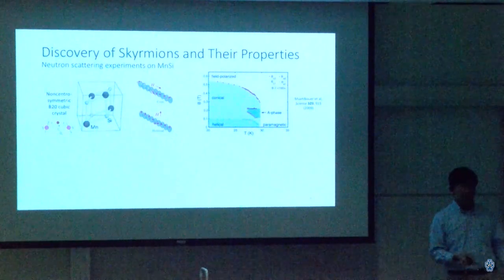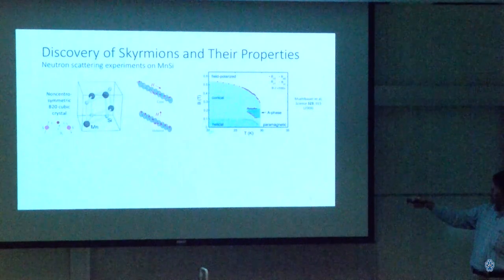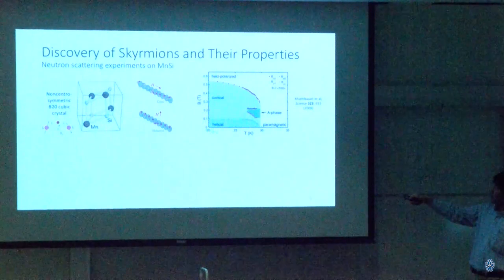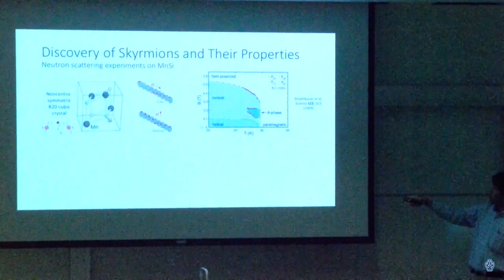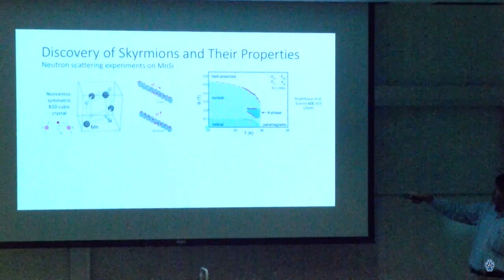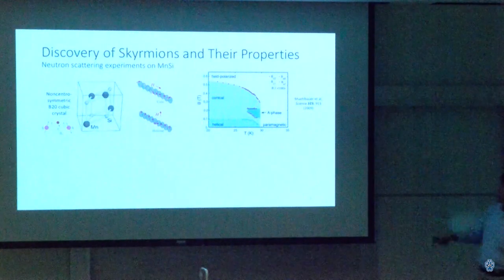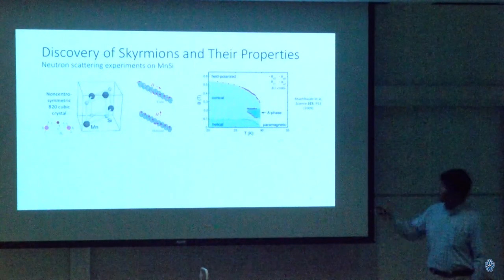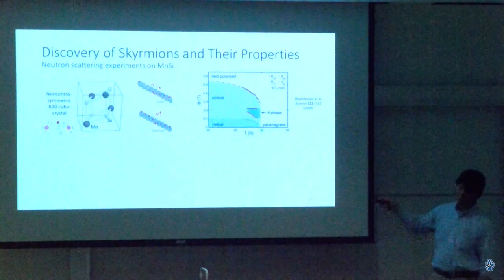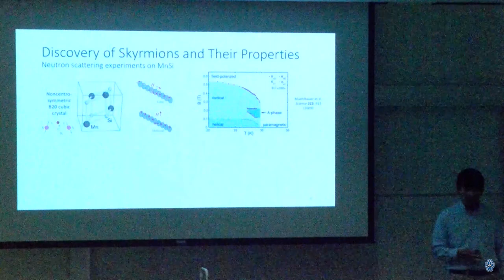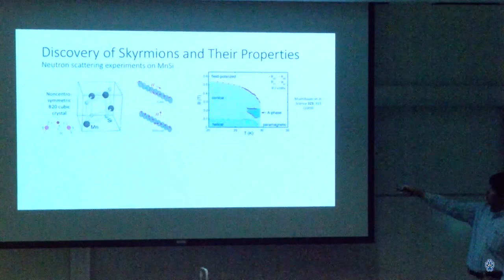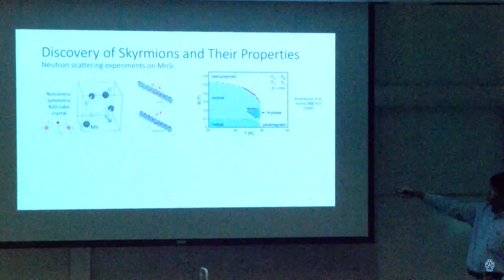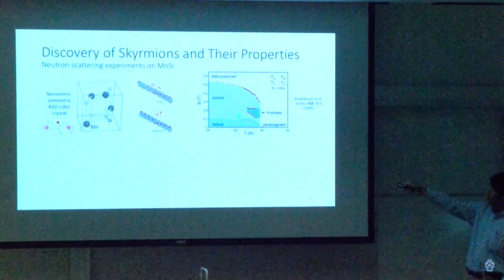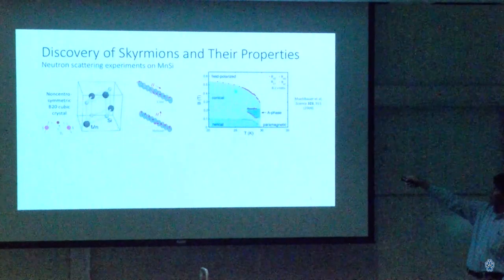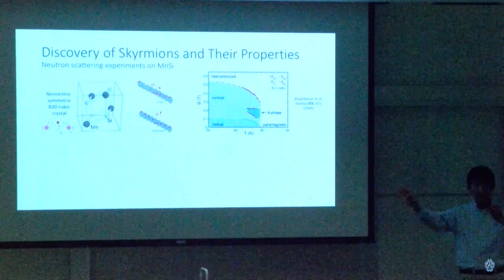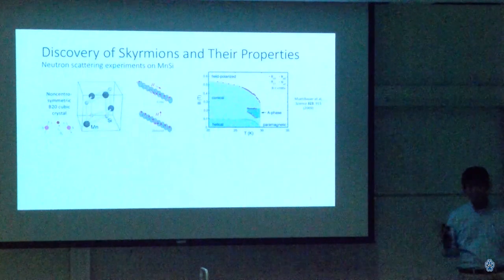I went into detail to describe them because that's what appears in this phase diagram, in which we map the magnetic properties of manganese silicide against the temperature in the horizontal axis and applied magnetic field along the vertical axis. So you'll note all this occurs at very low temperatures, under 30 Kelvin. But once you can get below that temperature, a whole wealth of things happens. At moderate magnetic fields, you have the helicoidal spin texture appear. You increase the magnetic field at low temperatures, you can go to conical, and then eventually the field becomes so strong, it just makes all the spins point along the direction of the field.